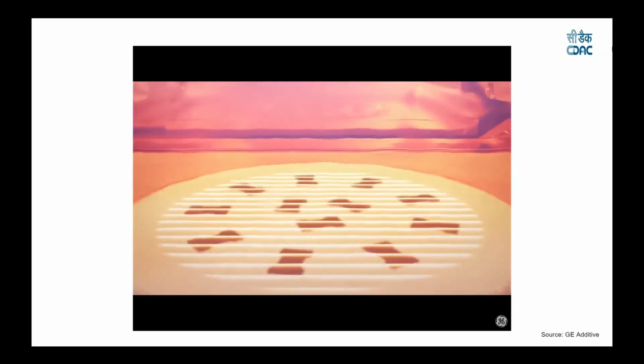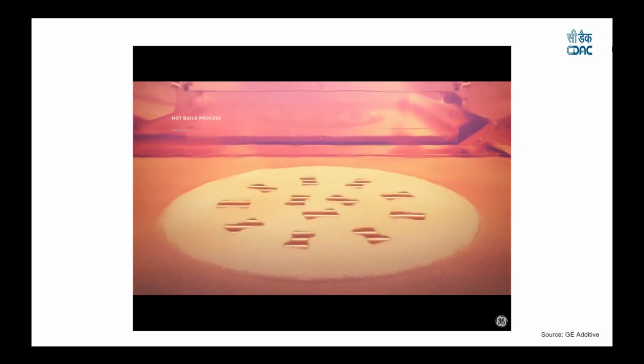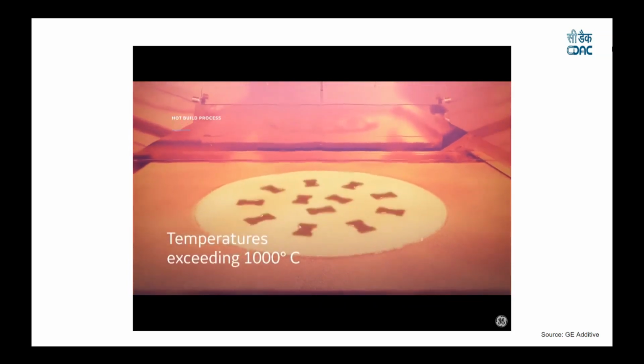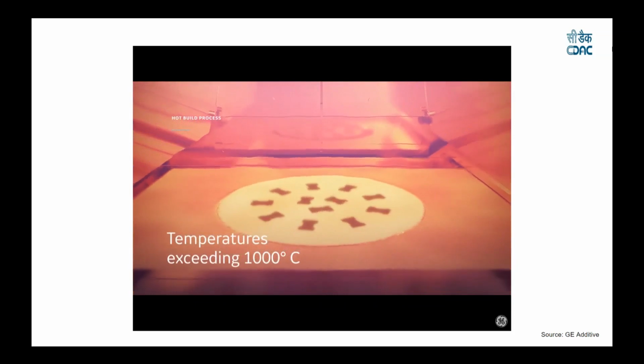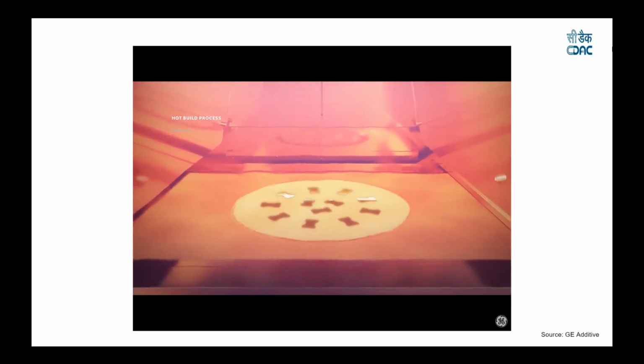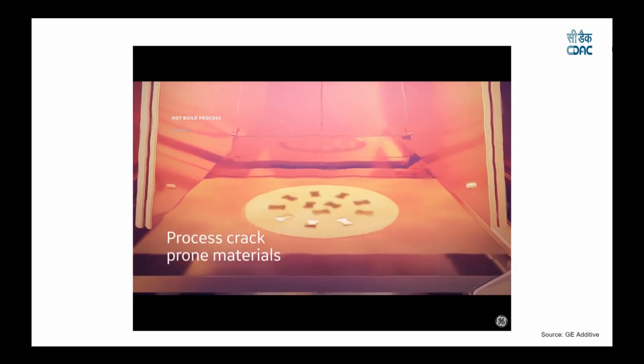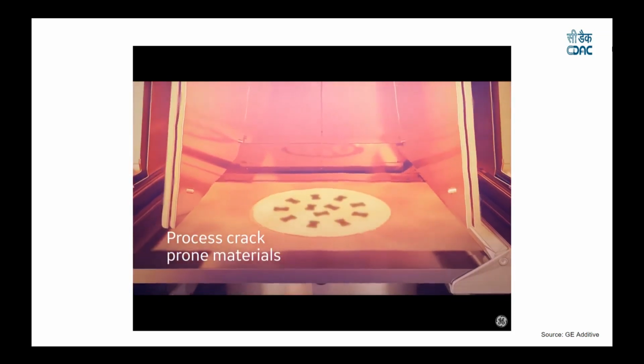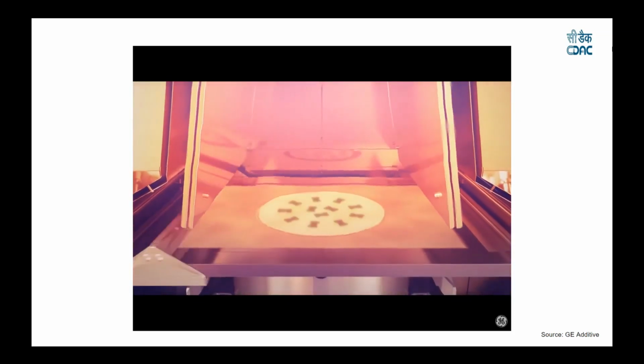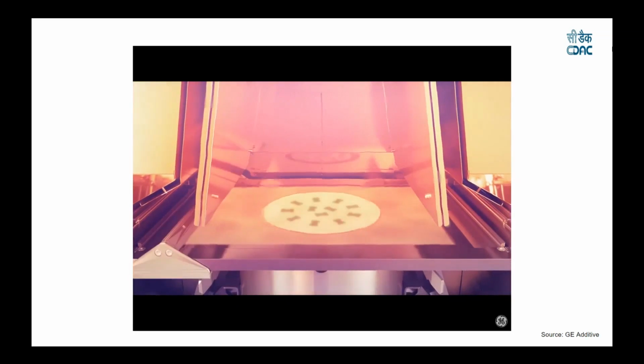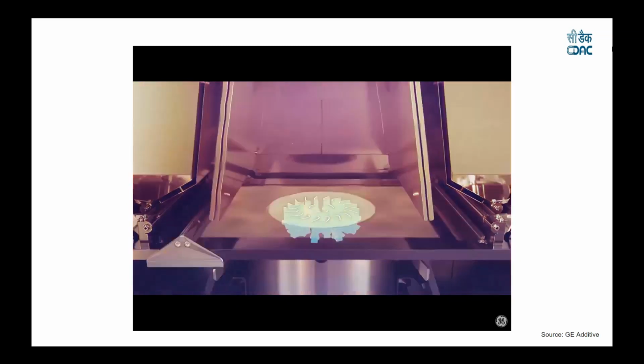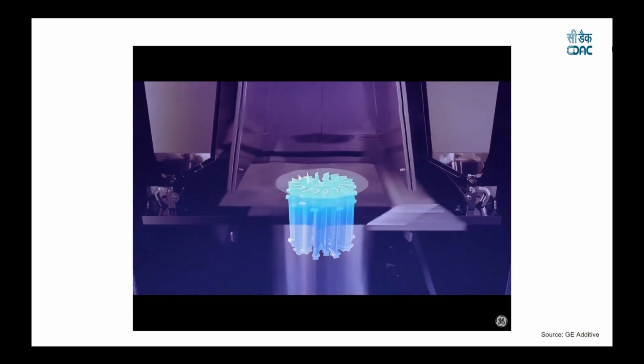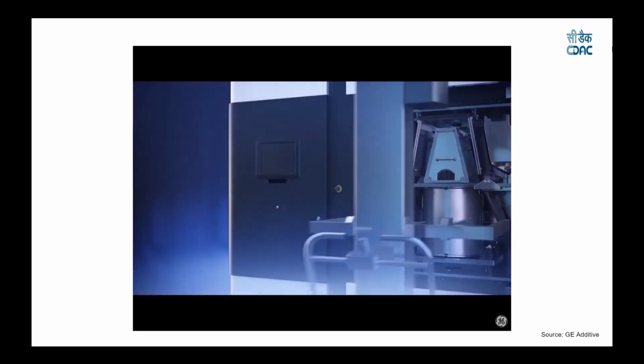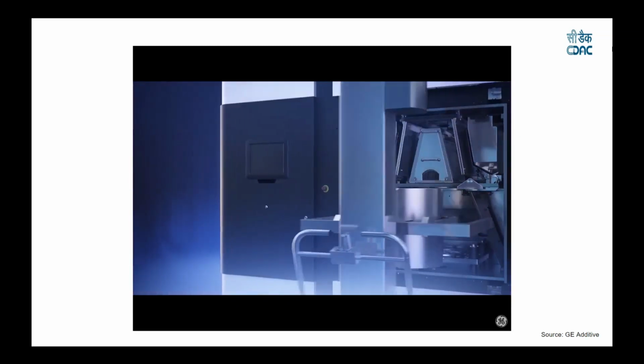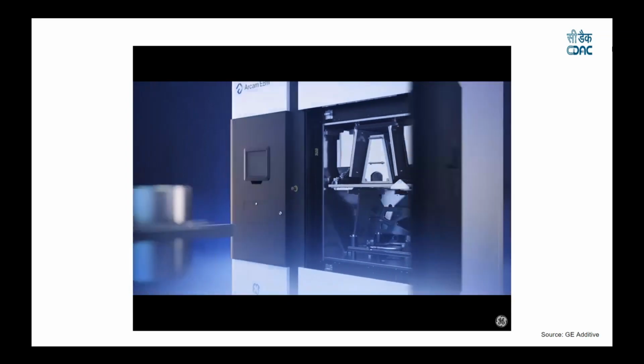The build environment is kept hot, reaching temperatures exceeding 1000 degrees Celsius, resulting in no residual stresses and allowing for the processing of crack-prone materials. So as the temperature inside the chamber is high, we do not have to provide support such that the build won't warp. As each layer is completed, the build is lowered and a fresh layer of powder is raked over it. This process repeats, growing the build one layer at a time. When the build is complete, the tank is extracted and the Arcam EBM machine is prepared for the next build.